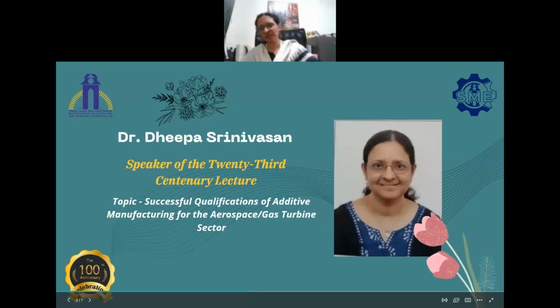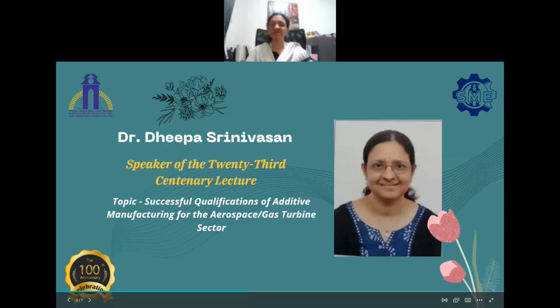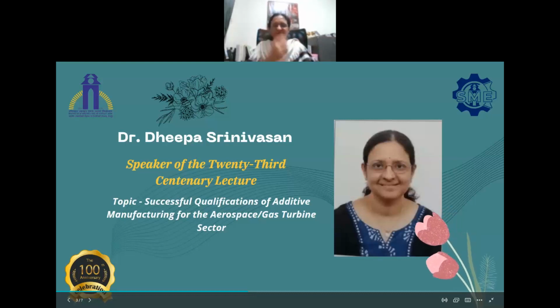Full blade, to my knowledge, people have not made yet with additive, because the heat transfer is so complex. In order to maintain single crystal, typically we seed it and then we grow, in investment casting. It's very difficult because of the rapid solidification in additive manufacturing. Directionally solidified, there is a little more success. OEMs have made some through direct energy deposition more than laser powder bed fusion. But to my knowledge, again, nothing is qualified and in the engine yet.